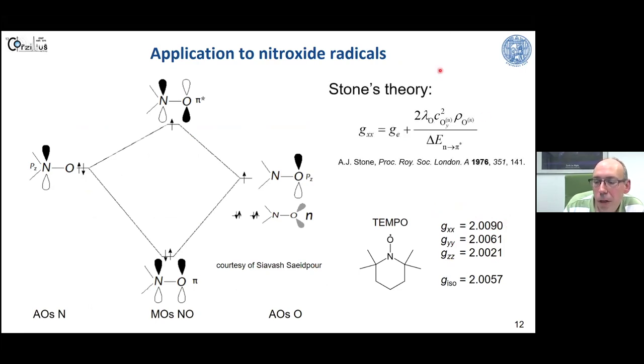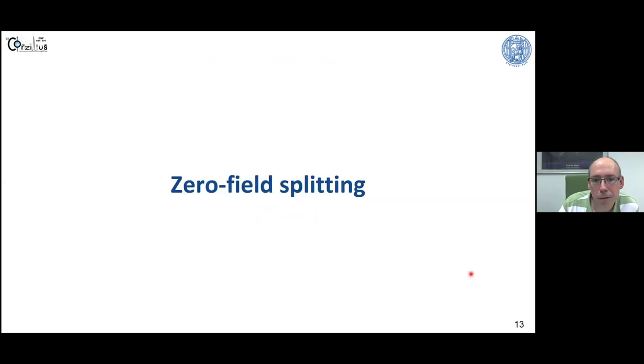And you can model this practically with a simple theory, where you take this kind of excitation, let's put it like this. You excite one non-bonding electron from the lone pairs in the oxygen into the pi star orbital, so the antibonding orbital of the nitroxide. And then you create a degenerate excited state, because these two lone pairs are degenerate, and this means you have an orbital momentum in this state. And this then causes the deviation of the g factor in nitroxides. This is very quickly abridged, but this is the whole idea behind this.